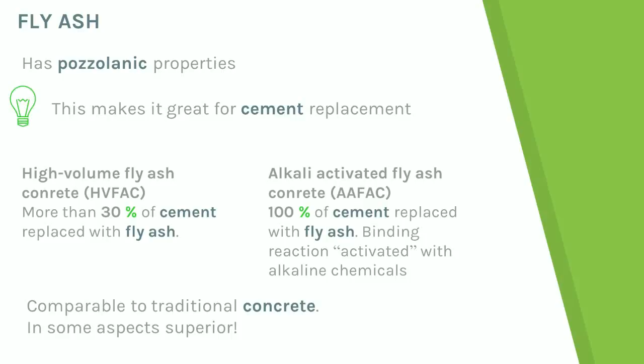Having this in mind, it is reasonable to assume that the replacement of a certain amount of cement by fly ash will not have negative effects on concrete. Such concretes in which more than 30% of cement is replaced by fly ash are called high-volume fly ash concretes. Because the pozzolanic reaction is slower than cement hydration, high-volume fly ash concrete has a slower strength development than ordinary cement concrete, which has to be taken into account. The benefits of using fly ash include better workability due to a finer packing density of particles and improvement of certain durability-related and long-term properties such as shrinkage.